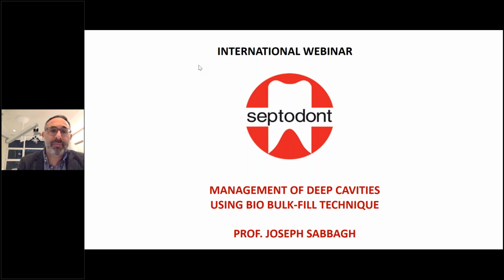Independently of Biodentine or not, what we are looking for when waiting 4 weeks is to make sure that we don't have any clinical signs and that the patient does not need to have a root canal treatment, because we know that if we do direct pulp capping, in case I will consider or discuss the direct pulp capping, we have a risk of failures. Sometimes it's 20-30% according to the indication, to the age of the patient, and to the size of the exposure. We did not discuss all of the issue.